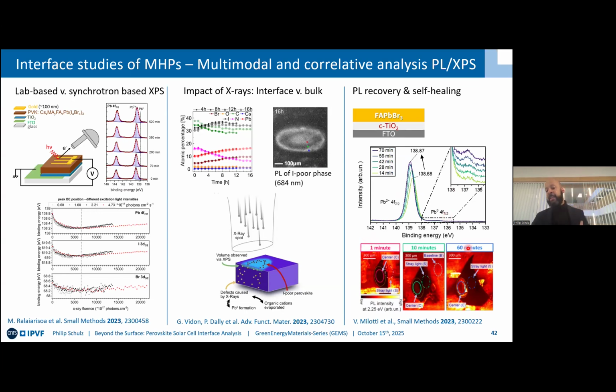But what was actually even a bit more intriguing is once we received the samples exposed for either 1 minute, 10 minutes or 60 minutes to the beam, you could actually see in a PL image the beam profile. So it's actually this small oval spot here that is the beam. You have a little bit of shadow that is an overshoot from the X-rays passing the different lenses effectively. And then you can see that as you increase the X-ray time, and then take the image afterwards, you can already make out a small change in this region. And it even shows this strong recovery of photoluminescence for long X-ray exposure, which we found as stimulated self-healing.